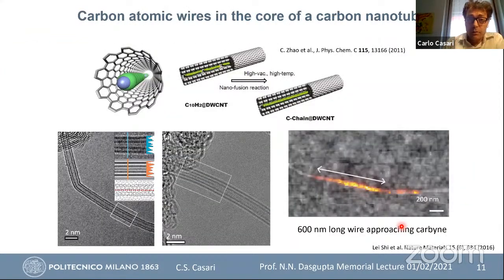The possibility to have the single chain inside carbon nanotubes is very appealing because carbon nanotubes are able, in some way, to protect the linear chain against reorganization. And so in this way, it's possible to make very long chains, as was done by Lei Shi and his group. I want to show you here this example of a way to use the nanotube as a sort of reactor. So by putting short chains inside the nanotube, and then by a thermal treatment being able to produce the connection between the different short wires into a longer one.